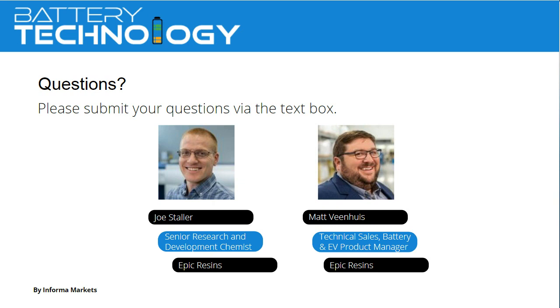Very good. And do you have a low temp, approximately 60 to 80 C thermal cure epoxy or epoxies, and how long is cure time? Sure. That's going to depend on the chemistry that we use. When we're talking about epoxy cure time, that's dictated primarily by the curing agent that we're using. So the short answer is yes, and we can formulate to accomplish the cure time you want at the cure temperature that you want as well.